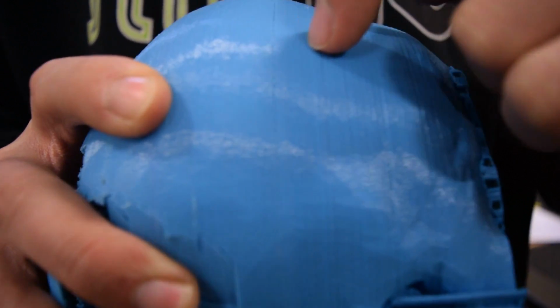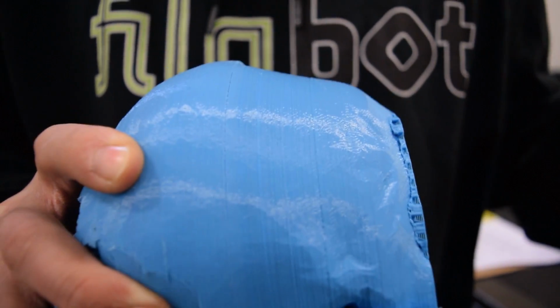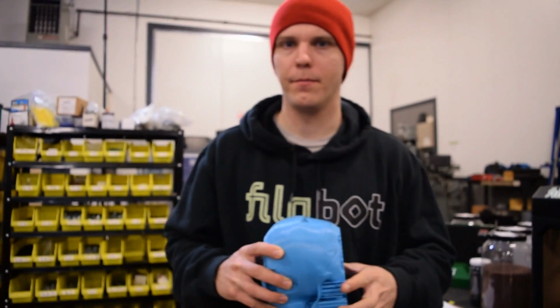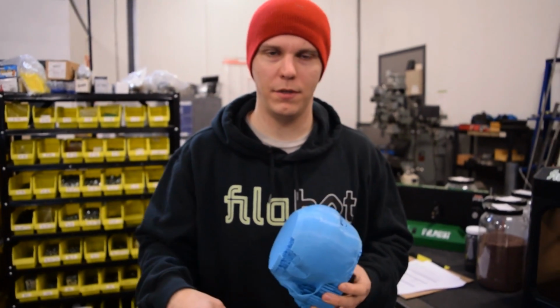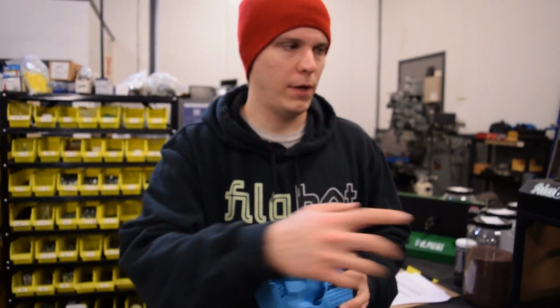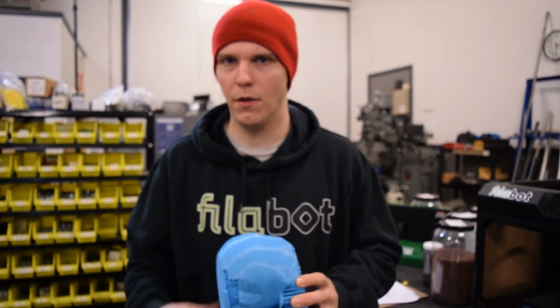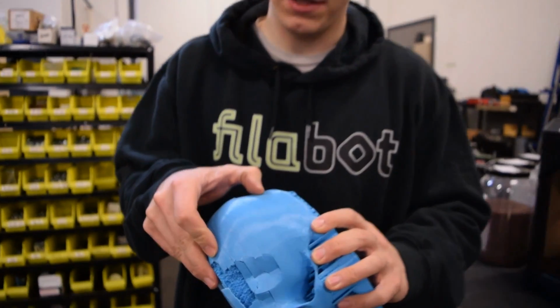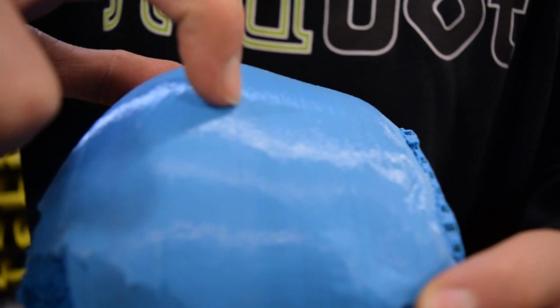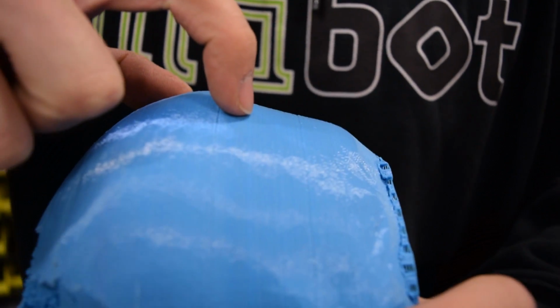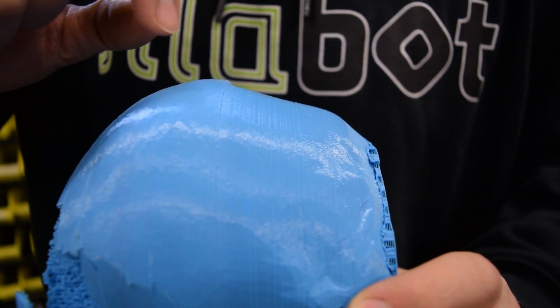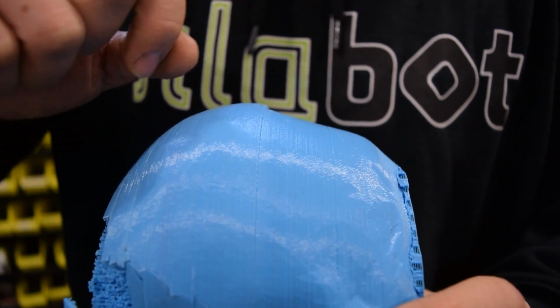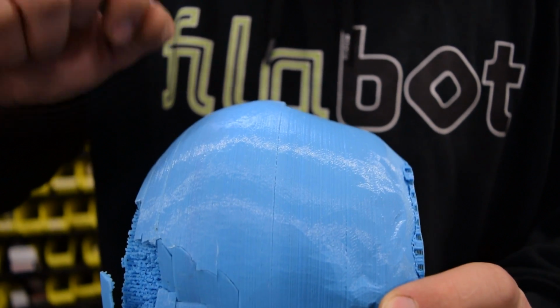And the other issue is if it's changing, you're going to have variation in the output of your extruder. Most extruders, the desktop versions, don't have feedback for the diameter of the filament that's going into the printer. So having a very tight tolerance on your filament is important, because the gear that pushes the filament down goes at a constant rate, because it assumes the filament's in a constant diameter, which means it's a constant volume going through the extruder. If that volume is changing, you'll have less volume coming out at certain points. You can see this one really clearly, where there just wasn't enough plastic coming out of the nozzle because the diameter got too small.